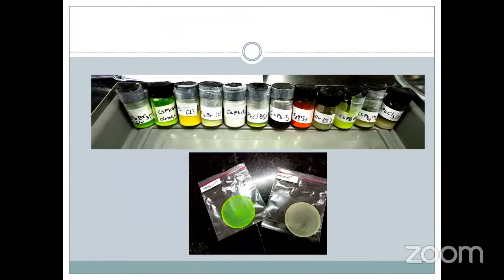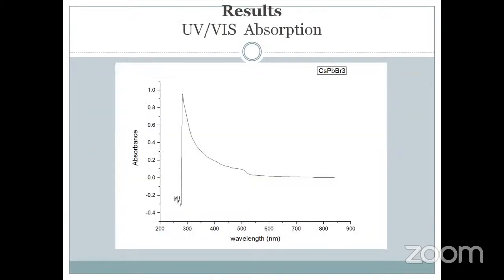Here are the images of samples which I have prepared with the same method, and the film was also prepared by dissolving polymethyl methacrylate in quantum dots already dispersed in toluene. So for the optical properties of CsPbX3 nanocrystals dispersed in toluene, UV-visible absorption and PL spectra were recorded. Because of the time limitation, I could not show all the graphs of the samples which I have synthesized. So I have shown only the graph of CsPbBr3.